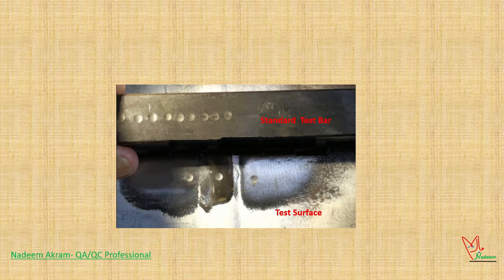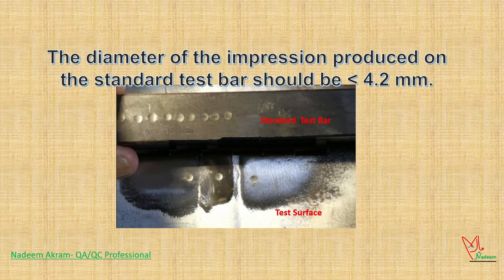The diameter of the impression produced on the standard test bar should not exceed 4.2 millimeters.